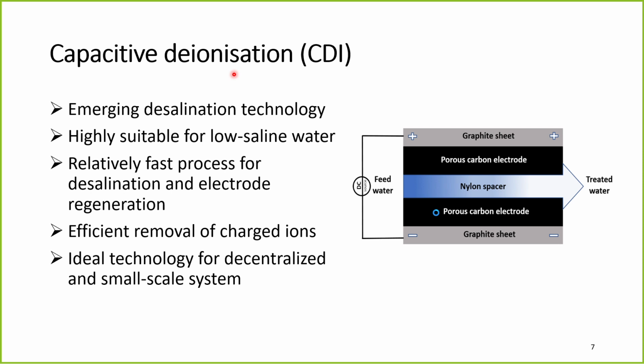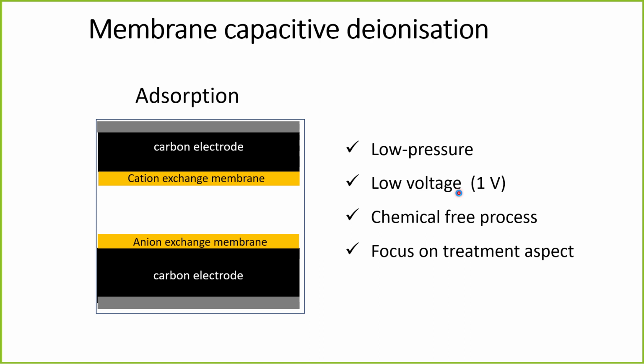This is an emerging technology, highly suitable for low salinity, a relatively fast process, with efficient removal of charged ions, ideal for decentralized small-scale systems. We have a graphite sheet and a carbon electrode, which is powdered activated carbon, and a spacer, which is the water channel, and we have an electrode and a graphite sheet. We apply a direct current, plus to minus, and then you can separate your ions. This is membrane capacitive deionization.